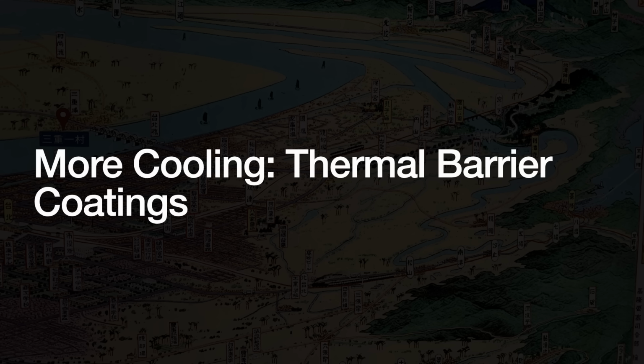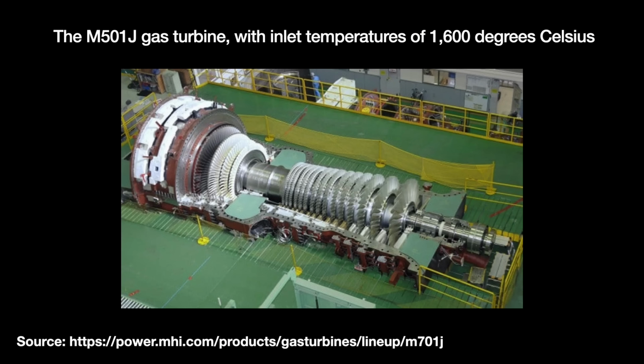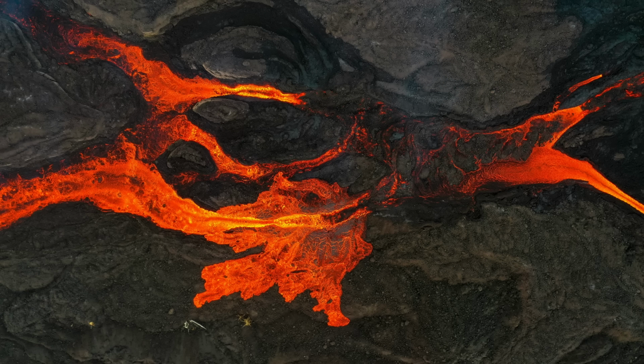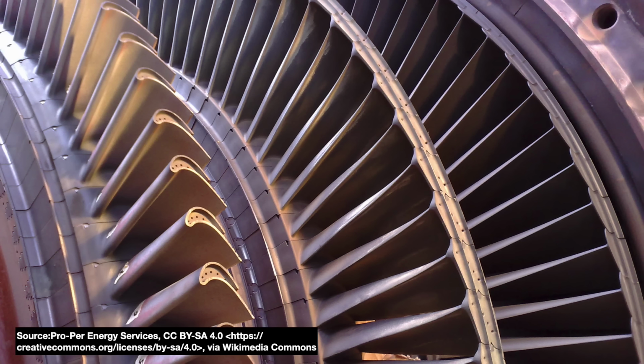One of the most advanced combined cycle gas turbines today is the Mitsubishi J series, with an efficiency of about 64%. Its operating inlet temperature is 1,600 degrees Celsius. That is hotter than typical lava and 3 times hotter than a pizza oven. It exceeds the melting points of steel, cobalt, and nickel, meaning that even the superalloys will melt at such temperatures. So, how does the turbine not melt down?